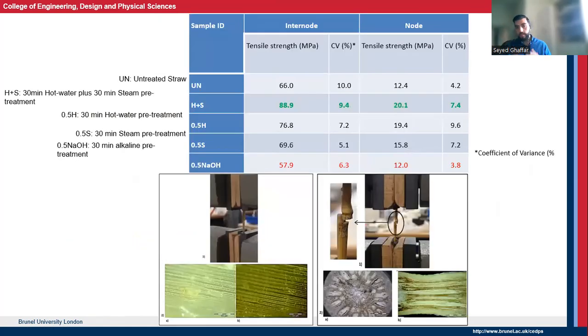So I looked at, in the context of biocomposite, this project was essentially developing a composite for the built environment. We looked at the tensile strength. This was very important for us. So the tensile strength of the internode and node, you can see there is a huge difference between the tensile strength of the internode and node for the case of untreated straw. So as received, as harvested from the farm, the internode tensile strength is around 66 MPa, whereas the node is only 12.4. So node is not designed in a way to be able to sustain any tension.